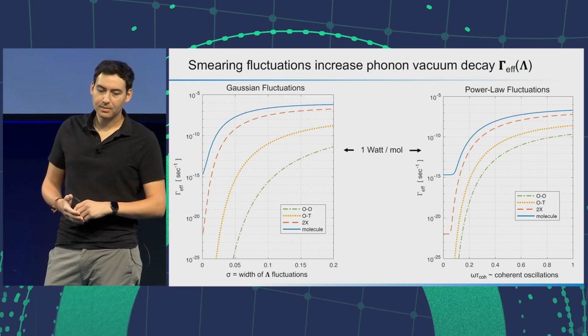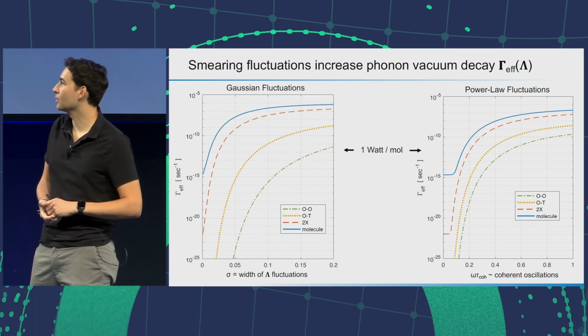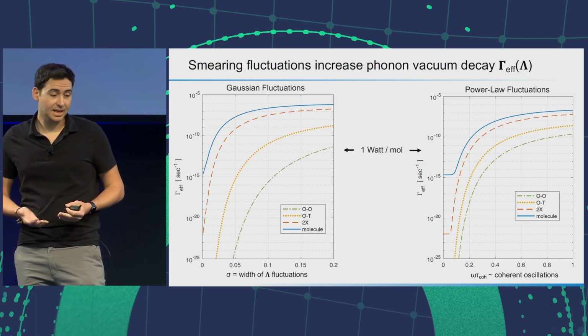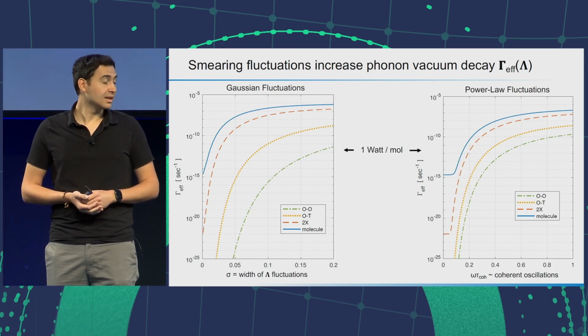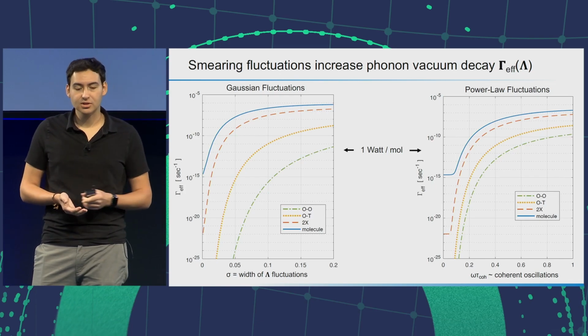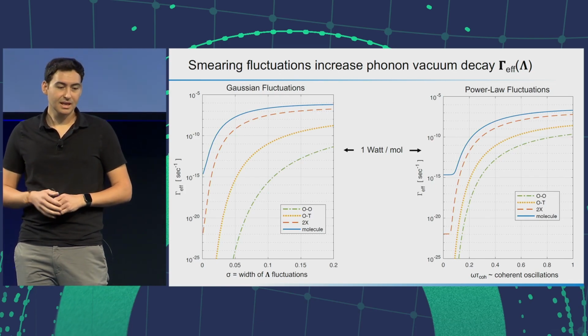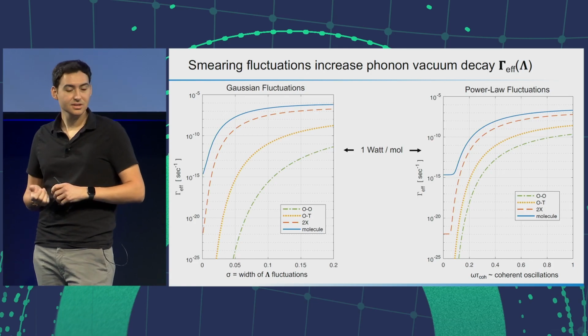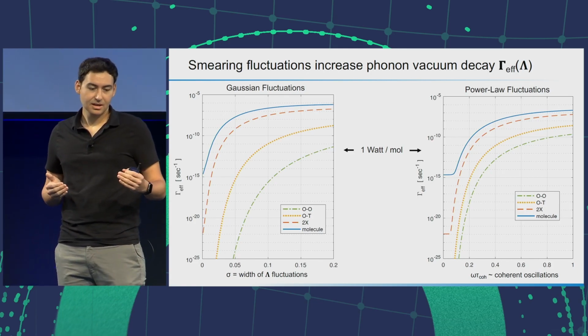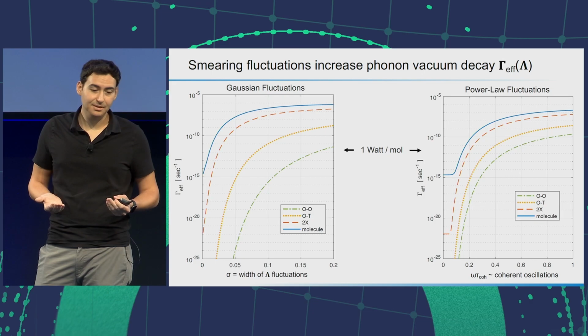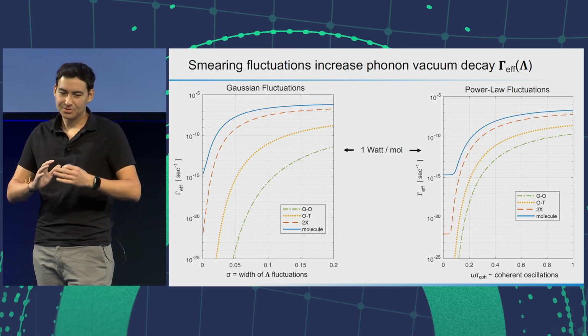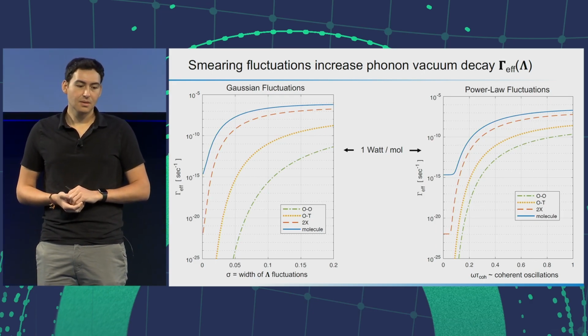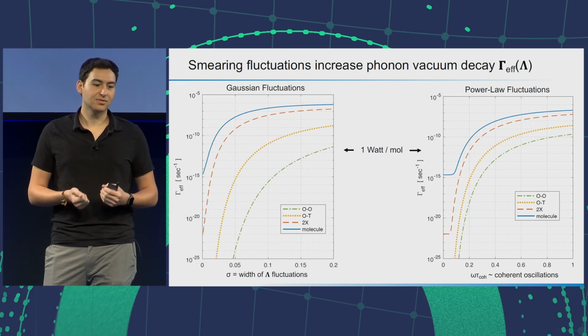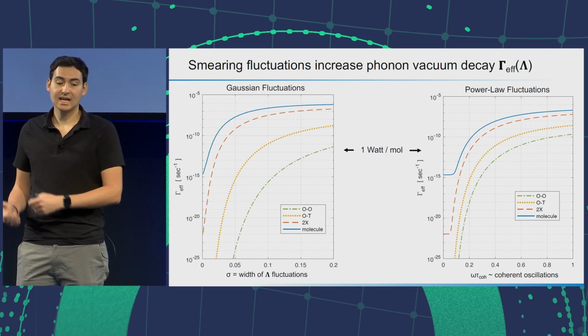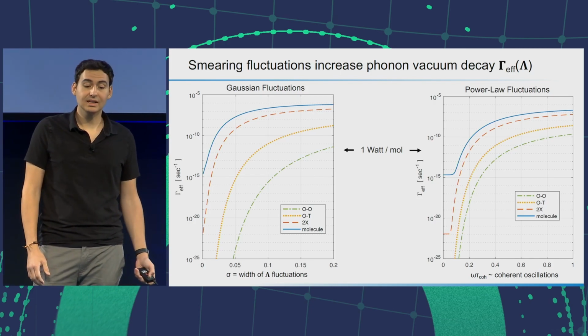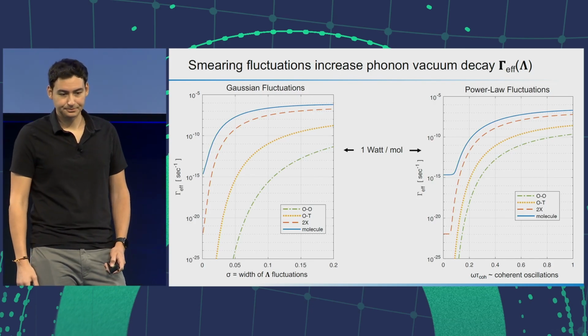On the right, it's a more microscopically motivated model, power law fluctuations. But the result is the same. We see on the vertical axis the effective fusion rate, inverse seconds, as a function now of strength of fluctuations. And so we increase the strength of those fluctuations, and we see in all cases we can cross this threshold more easily. The particular numbers here, again, don't matter so much. I won't go into the details, but I hope the takeaway is clear: when we introduce fluctuations to our system, we can enhance the tunneling probability significantly and the effective overall fusion rate.